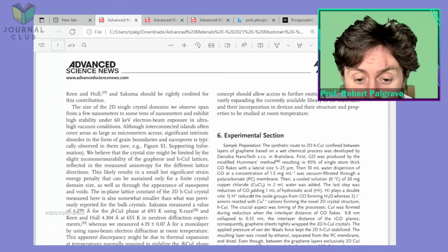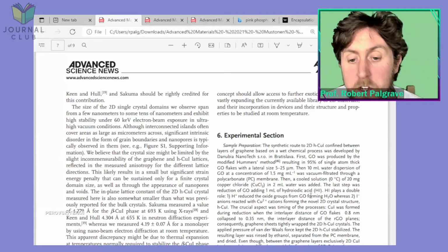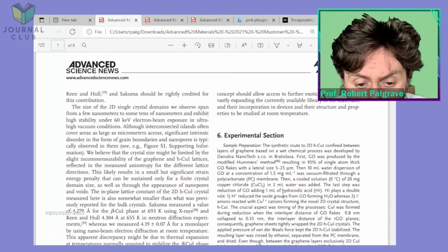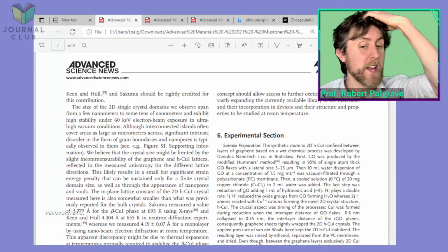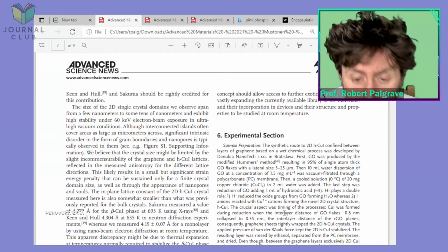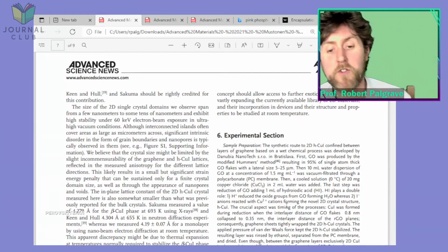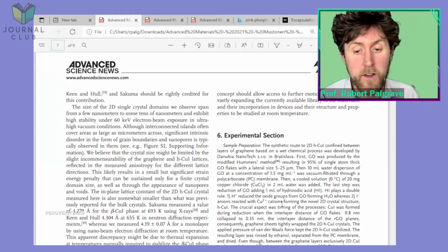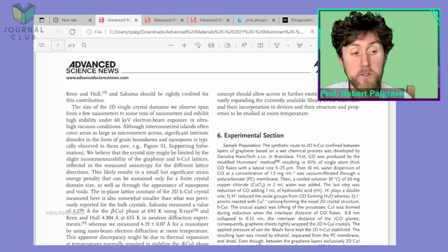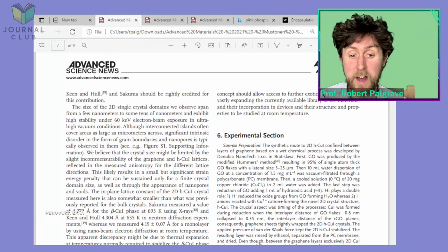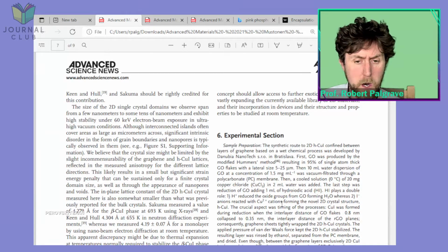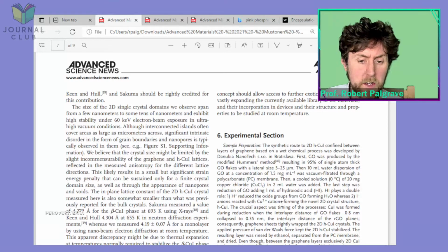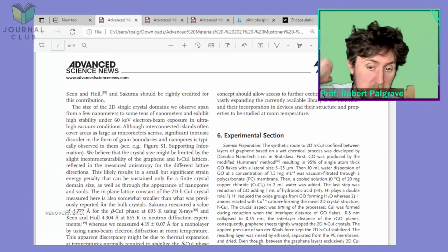HI plays a double role. H+ reduced the oxide groups from GO, forming H2O, whereas two iodide ions reacted with copper 2+ ions, forming the novel 2D crystal structure h-CuI. I don't think they address the fact that they're reducing the copper and the graphene oxide at the same time. Of course the copper is going from 2+ to 1+. So HI is doing both of those jobs at the same time.